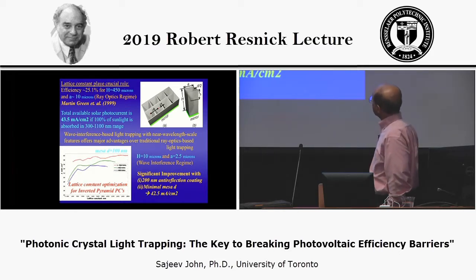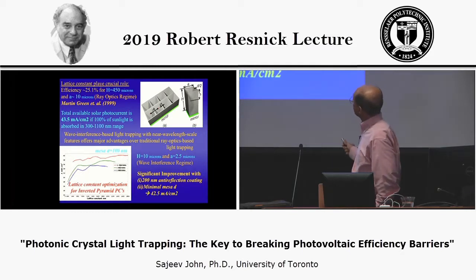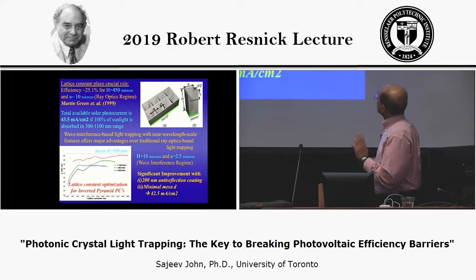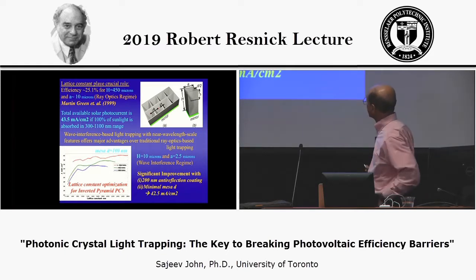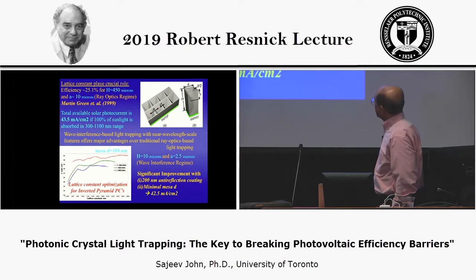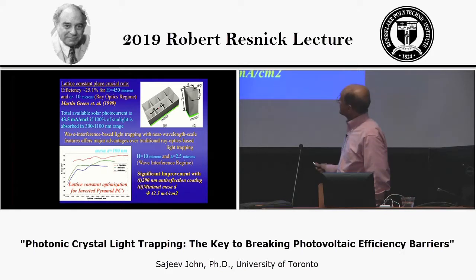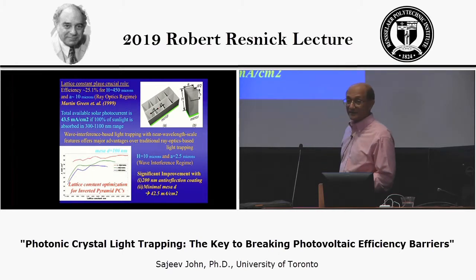And what we were able to show is that there's considerable wave interference that takes place in this structure. And for a 10 micron thick structure with 2.5 micron lattice constant, if we also put in a thin layer of anti-reflection coating on the surface to prevent some of the very short wavelengths of light from being reflected, we could bring the maximum achievable photocurrent density up to 42.5. And that's actually very close to the maximum possible, which is 43.5, which would correspond to 100% absorption of sunlight in the 300 to 1100 nanometer range.